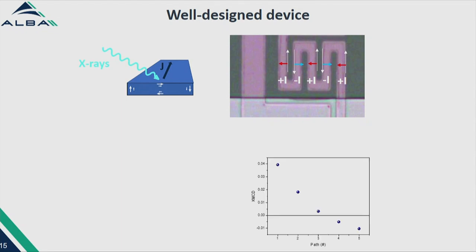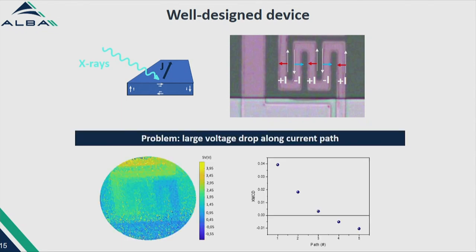First attempt. What happened? We are working with low energy electrons, and it seems that the local voltage on the surface, the voltage drop needed to have a current, was creating a background that was orders of magnitude larger than the signal we were looking for.